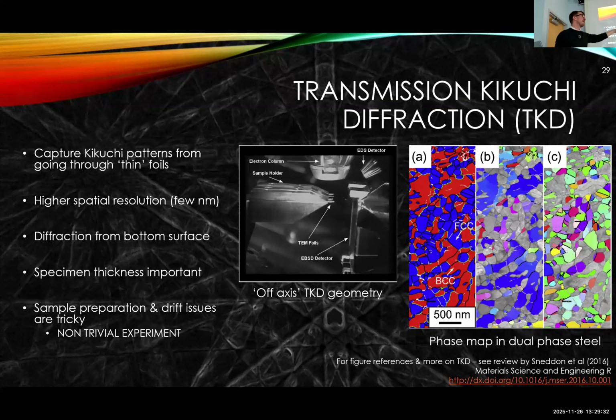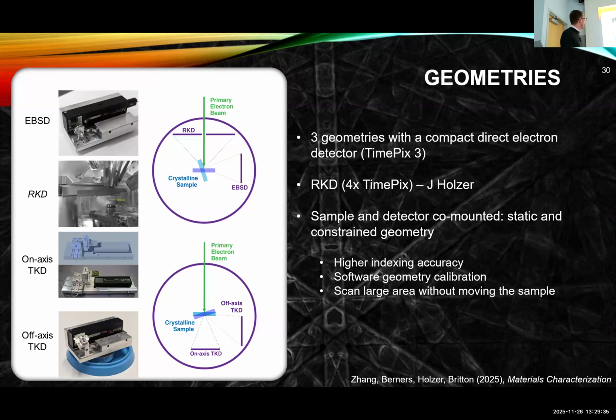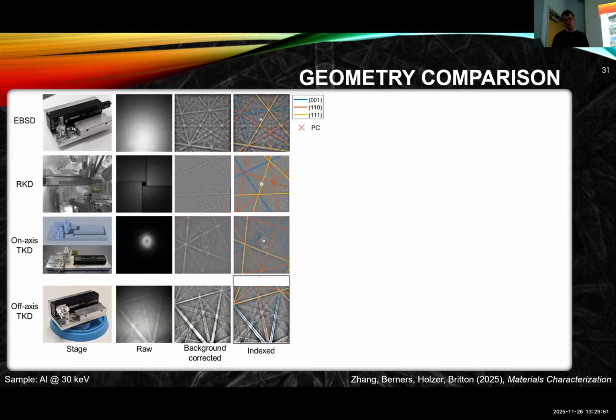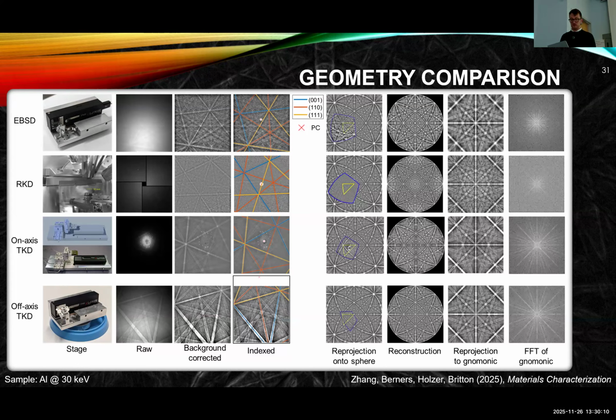So that's the sort of setup that they showed sort of worked. We did this, and we used a series of compact detectors. So this is our detector. This is what we're getting. This is our TEM on-axis TKD detector, and this is an off-axis TKD detector. And so we did this work. It's been published in Materials Characterization. And we have our own software algorithms to do all the indexing that we can just run all the data through. And here we have the raw patterns. Here we have the diffraction patterns background corrected. And then we have the indexed diffraction patterns for all of those geometries. So we can see that there are benefits and disadvantages to the geometries.